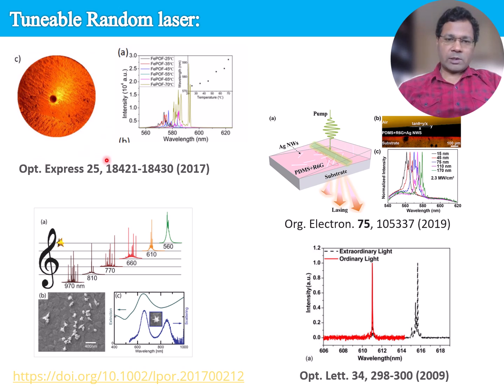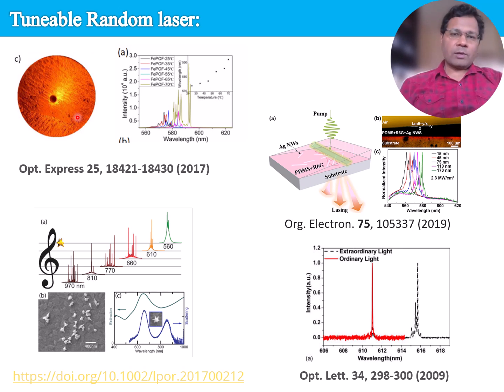Tunable random lasing has been demonstrated in various systems. One of them is this polymer optical fiber. Temperature controlled spectral tuning in random lasing was demonstrated in optical fiber which is doped with dye and nanoparticles. The lasing arises here from multiple scattering within the fiber core, and due to the high thermo-optic coefficient of the polymer, temperature changes tune the refractive index, causing a red shift in the lasing spectrum.